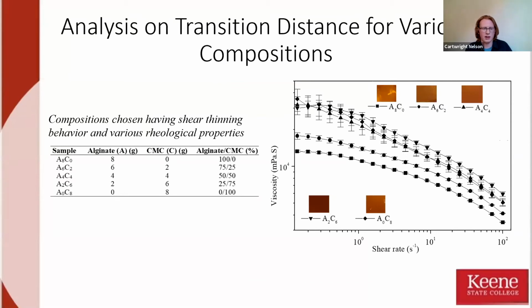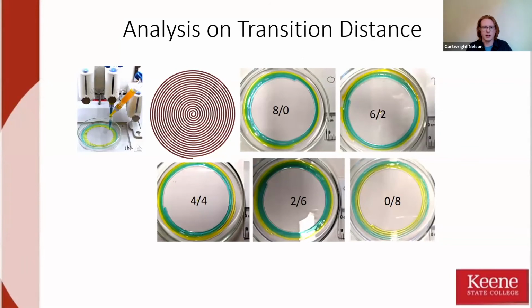All right, so the 5 different compositions that were used were tested for the rheological properties, and one of the big ones is viscosity. The one that showed the least viscosity was 8% alginate and 0% CMC, because it didn't have that CMC to add viscosity. But surprisingly, this is not the best transition material. It's actually 6% alginate and 2% CMC, which is the second lowest viscosity. And all of these show shear thinning properties because of that downward trend in viscosity versus shear rate. So these are some of the spirals printed. And the printer that was used was a CellLink BioX bioprinter that was new over the summer. So that was really nice.